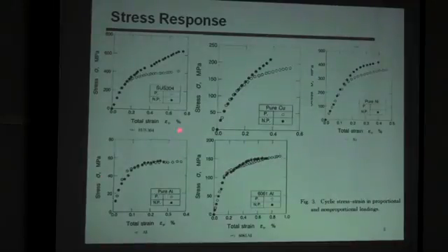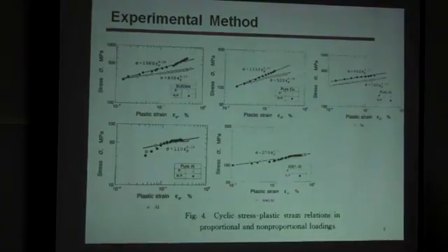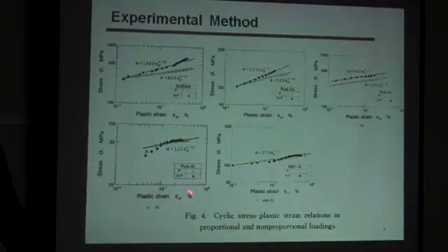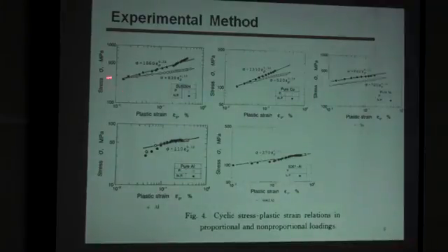And this is the result. This is stainless steel, and copper, nickel, pure aluminum, 6061 aluminum. So you can visualize very clearly: very high additional hardening here, medium, and no additional hardening here. And this is the stress against the equivalent strain range. So the same relationship we found for stainless steel, proportional and non-proportional. And additional hardening comes from the plastic strain, not the elastic strain.